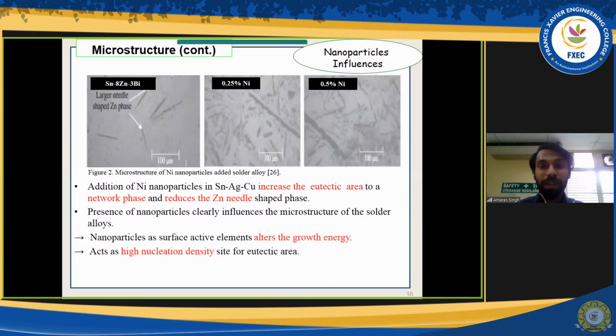So even in some cases, we can see that addition of nanoparticles actually tries to reduce the needle shaped zinc. So you can see the needle shaped zinc actually reduces upon addition of nickel nanoparticles, and they are a lot. So when they are a lot, they will try to be another source of strengthening effect.